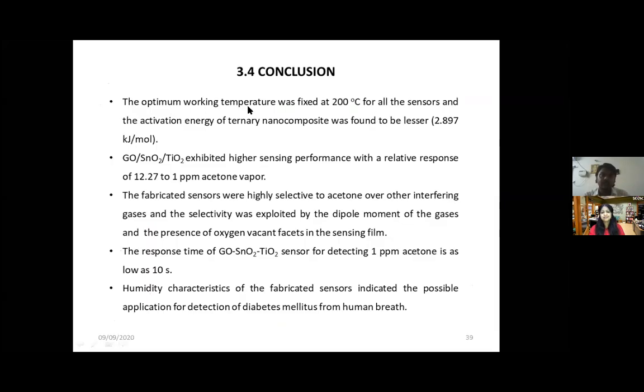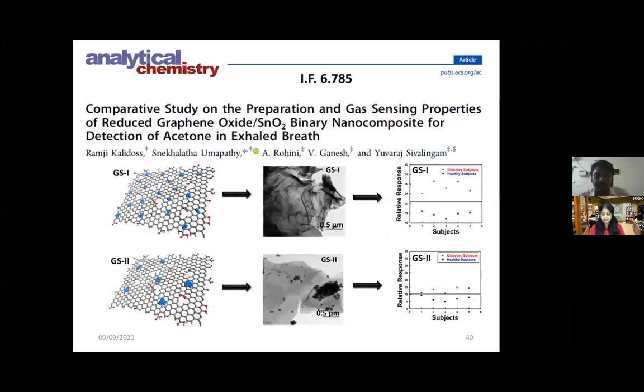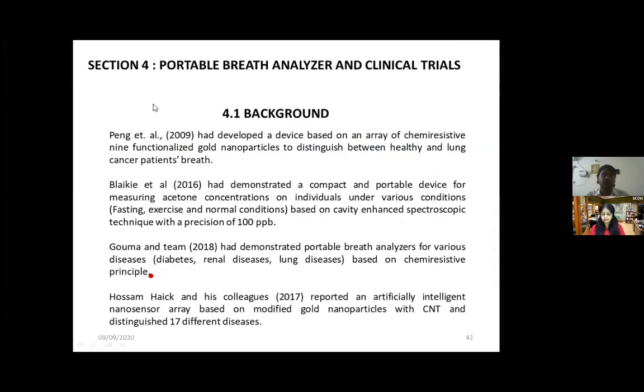So concluding this section, 200 degrees Celsius is the operating temperature, with the ternary nanocomposite performing better compared to all other sensors. The relative response is 12.27 to 1 ppm of acetone. And the selectivity is explained by the dipole moment and the dominant phase, that is, oxygen vacant facets of the sensing film. The response time is 10 seconds. Humidity characteristics tell us that we need a desiccant or a humidity compensation method. Stability characteristics tell us that we need to change the sensors at least once in 2 weeks. And this work got published in two journals. And we go to the next section.